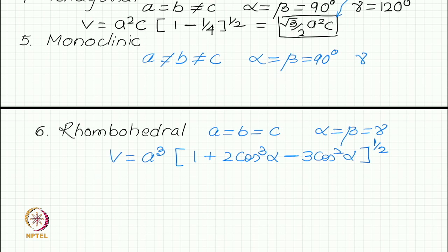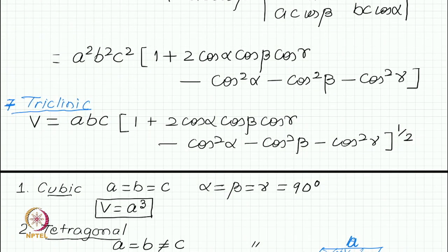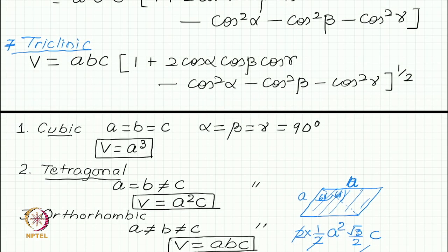We will show you that these are okay from unit cell size and shape point of view, but these are not the definition of the crystal systems. Cubic crystal system does not mean A equal B equal C, alpha beta gamma equal to 90 degree. I can give you a crystal satisfying these properties, but is not cubic.